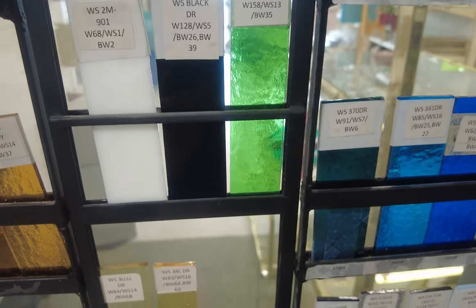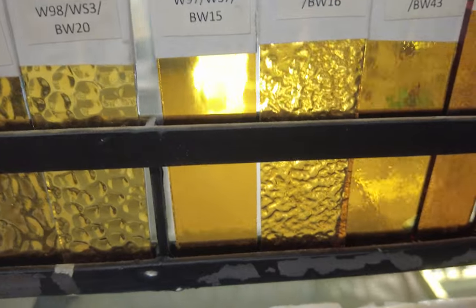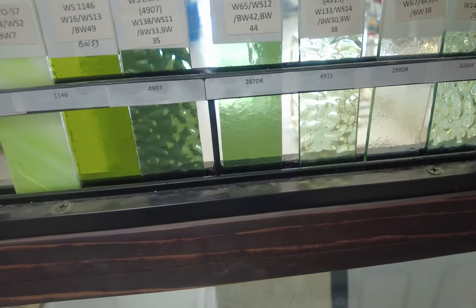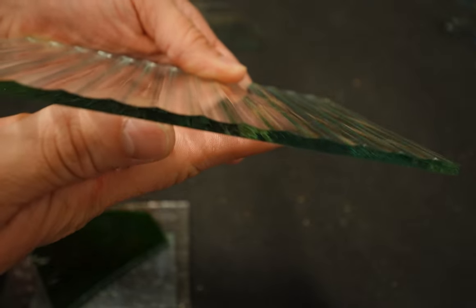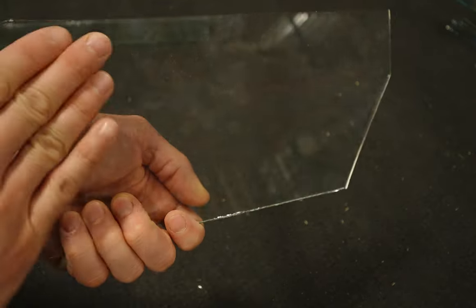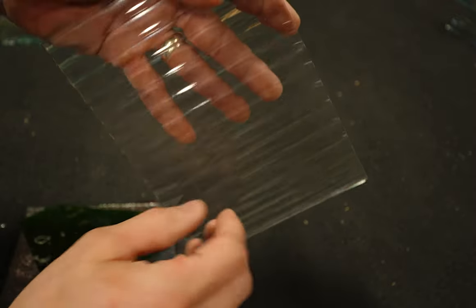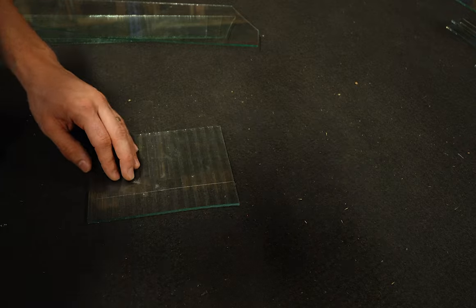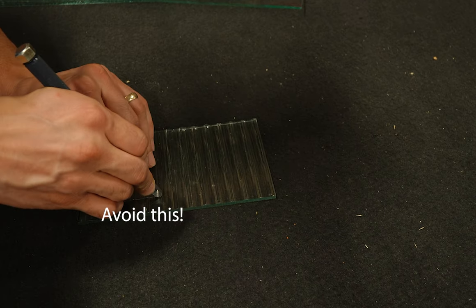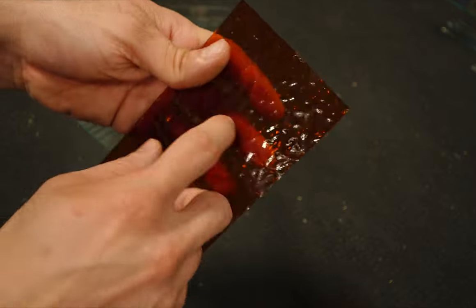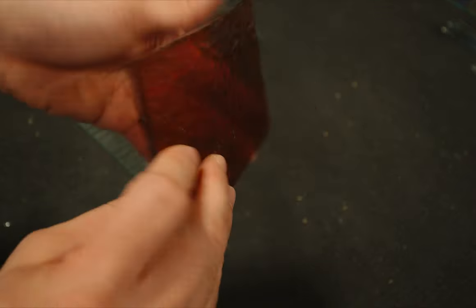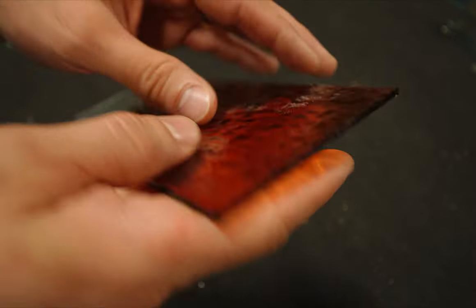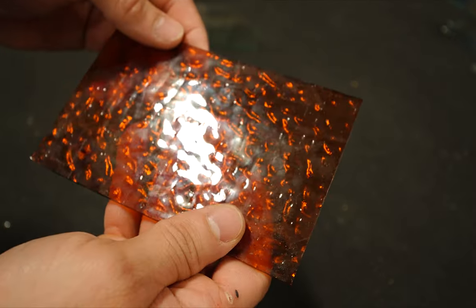You will notice that there is normally a smoother side and a textured side. So you will always want to cut on the smooth side so that your score is consistent and the glass has a greater chance of breaking smoothly along the score line. This clear float glass is perfectly smooth on both sides. The textured clear has a reeded texture every half inch on one side. As long as you cut on the smooth side it will cut exactly the same as the perfectly smooth glass. This amber glass is a good example of what you will commonly run into with stained glass. Again identify the smooth side and be sure to cut on that. Listen to the difference between scoring the rough versus the smooth side.